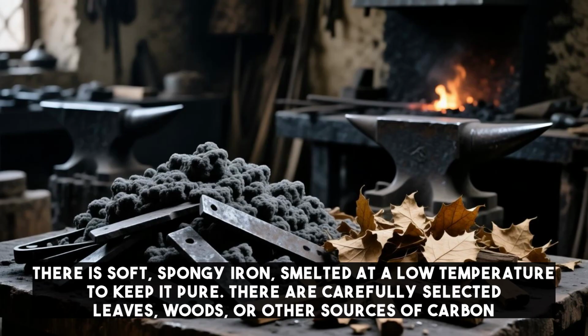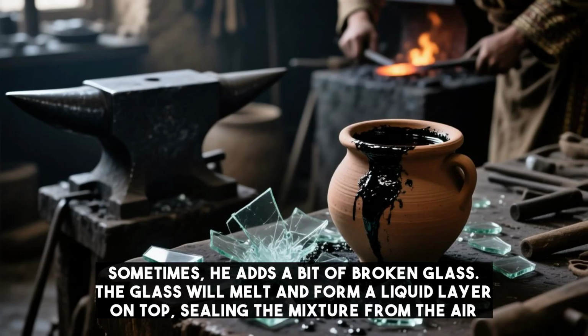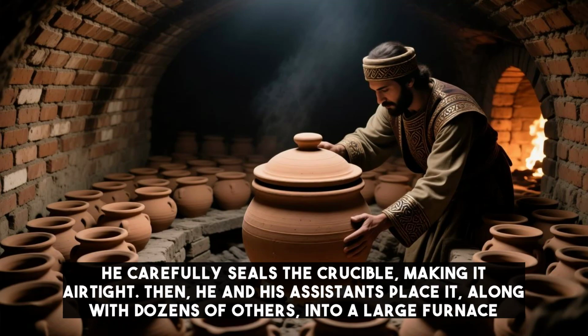And there is soft, spongy iron smelted at a low temperature to keep it pure. There are carefully selected leaves, woods, or other sources of carbon. Sometimes he adds a bit of broken glass. The glass will melt and form a liquid layer on top, sealing the mixture from the air. He carefully seals the crucible, making it airtight. Then he and his assistants place it, along with dozens of others, into a large furnace.